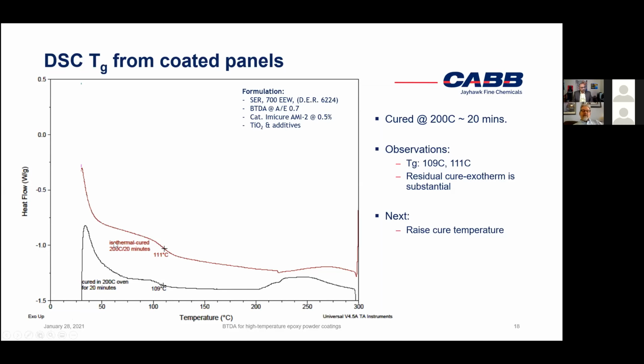All right. And then we also had a lot of uncured powder of the formulation. So that's where we started doing some crazy stuff ourselves. But before we went crazy, we wanted to just reproduce what was done in that last sample. So for this red or brown curve, we took the uncured powder, cured it for 20 minutes at 200 C within the DSC itself, and then scanned it to get this brown Tg scan. And we got basically more or less the same Tg. You have a residual exotherm at the high temperature. So very good reproducibility between a large scale oven cured system and a tiny DSC system.